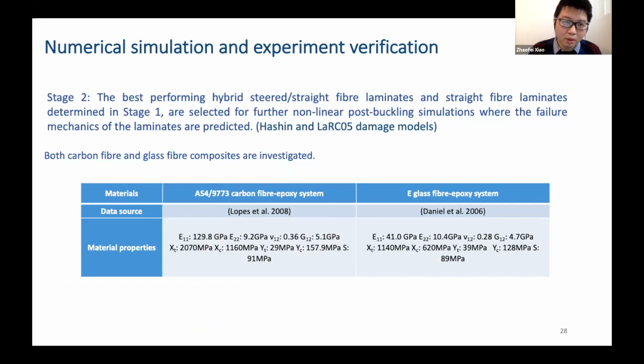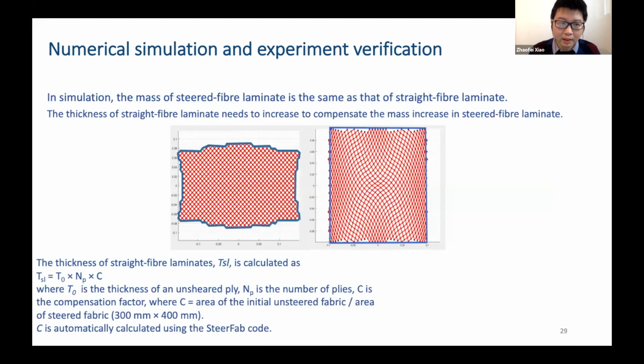At stage 2, the best performing laminates will be selected to do further non-linear post-buckling simulation to understand their failure. So both carbon fiber and glass fiber composites are investigated. I should mention that in the simulation, we want to keep the mass of the steered fiber laminate the same as the mass of the straight fiber laminate, because when you shear the fabric, you basically increase the areal density of the fabric.